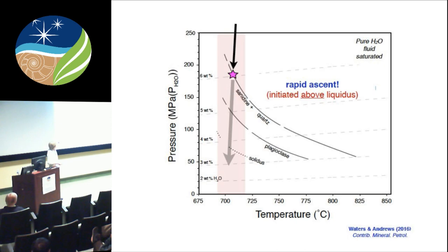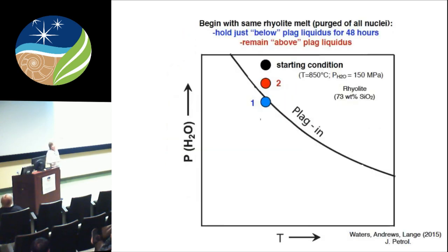So another set of experiments, starting with a low silica rhyolite, a different paper, starting above the plagioclase-in curve. This initial rhyolitic composition was first purged of all nuclei, taken in a furnace at 1 bar, really high temperature, and then put into this apparatus, pure water saturated, sitting up there. Both 1 and 2 started with where that black dot was. They all had the same beginnings. The first sample, 1, is held just at the plag-in curve for about 48 hours. When you quench it and take a look, it has very sparse plag because it's just at the plag-in curve.